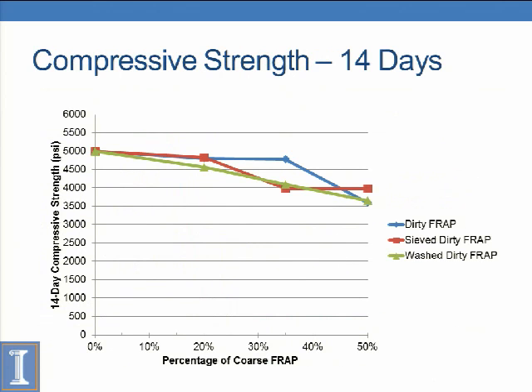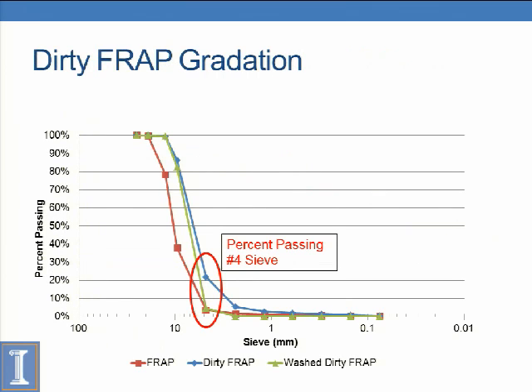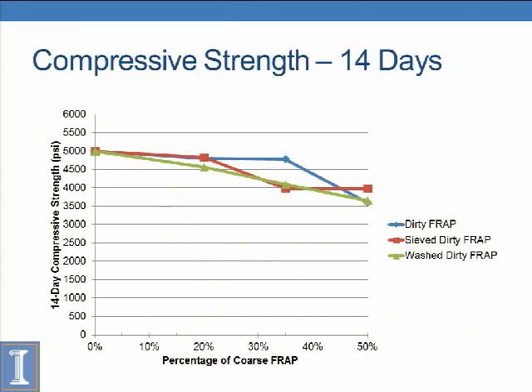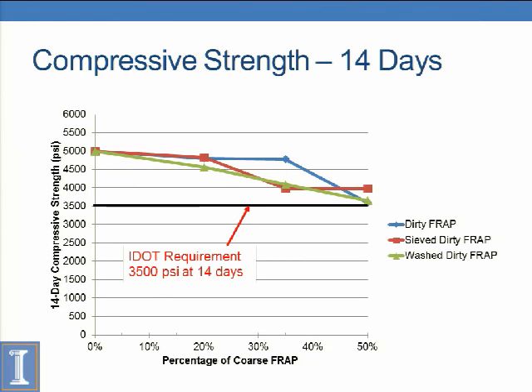And then what we did in the lab is we sieved to get rid of the fines, and we also washed it to try and get rid of the fines, which is what we see here on the gradation plot. This green line is after washing or dry sieving it. We get rid of a lot of those fines passing the number 4. So we wanted to see what was the effect of getting rid of these fines. Was it critical that we get rid of these fines? And pretty much what we found is it's not an issue to remove the fines. If we keep the dirty FRAP as is with the fines, we can see that it's higher than after we washed it and sieved it. So really we concluded that we shouldn't remove those fines.